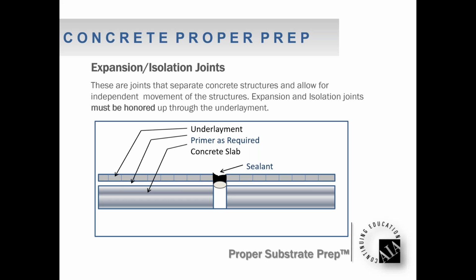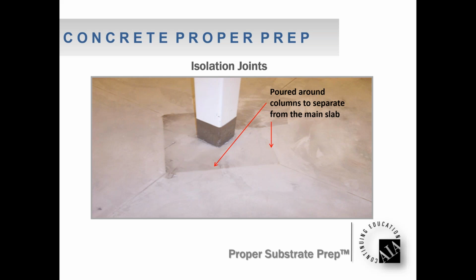If you don't, and the concrete moves and the flooring cracks, then you're dealing with unsightly floor covering. Here's a picture of an isolation joint. Typically a diamond like you see here, sometimes a triangle, but underneath that column is a concrete caisson that's supporting that column, and you typically got concrete poured all around. In this situation, unfortunately, they patched over it. Those isolation joints should be honored up through the patching material. Otherwise, you install flooring over it, it moves, and then you see unsightly cracking that's happening in the floor covering itself.